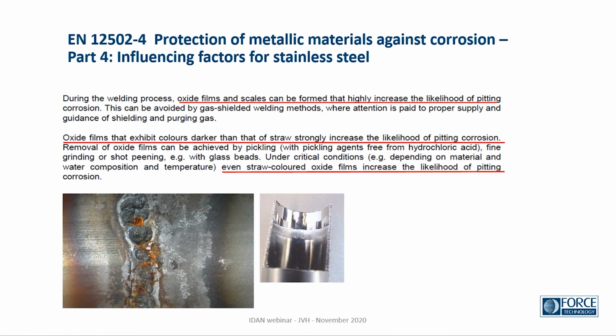Do we get any help from the standards to control this problem? In some ways, but not fully. We have a standard like this one, EN standard 12502 part 4 for protection of metallic materials against corrosion and stainless steel. It says that oxide films and scales highly increase the likelihood of pitting. So a red flag is pulled up to say you need to be alert, to be careful. And if you have colors that are darker than straw, then it strongly increases the likelihood of pitting. So there is an indication that we have problems, but this standard doesn't say that you can't have it. It just says that you should be careful.